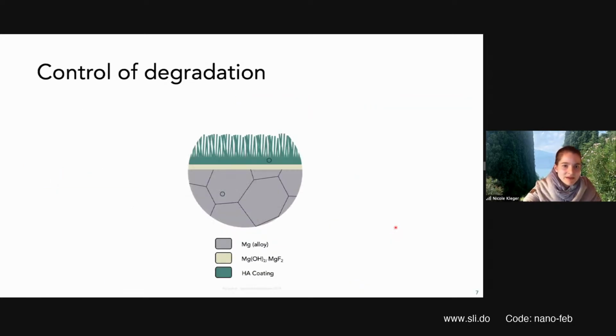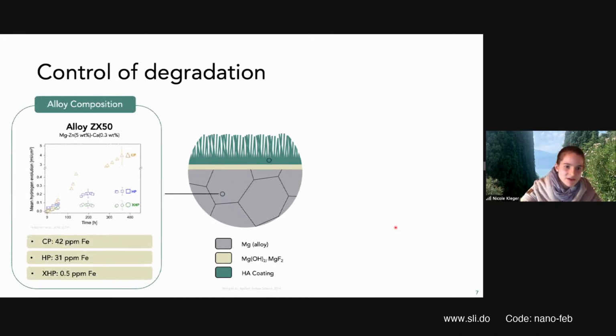Now let's look a bit more deeply into the corrosion of magnesium. So there are two main factors that can be used to control the magnesium degradation. One is the alloy composition. So what you see in this chart is the mean hydrogen evolution, which is a measure for the degradation speed, versus the time of immersion of a sample into a simulated body fluid. The orange triangles display magnesium of conventional purities, whereas blue and green are higher purity magnesiums.